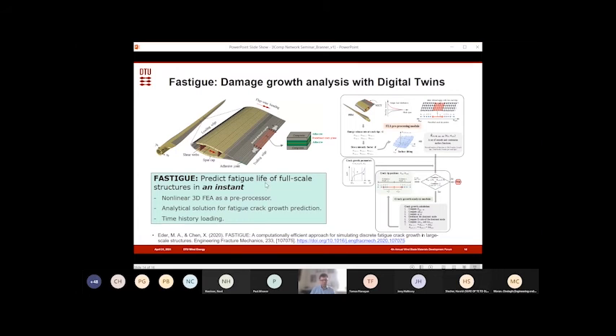A few colleagues of mine have developed this method called FASTIGUE, because of course doing these calculations can be quite numerically heavy. So this method is done to speed this up. Here's an example of a trailing edge damage, and this method can then be used with a non-linear finite element analysis, which is normally needed in these cases, to make predictions of what will happen with the loading history. And so this is part of coming to this idea of having a digital twin of a blade.